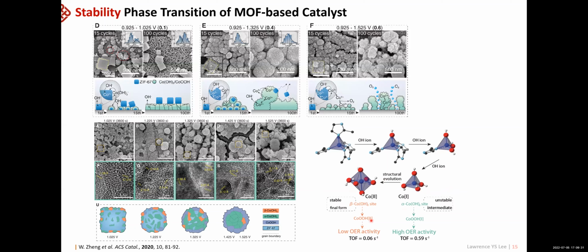So if anyone wants to use MOF directly for electrocatalytic reactions, you probably need to pay attention to their stability. I'm not saying the MOF is not a good electrocatalyst. They may be good pre-catalysts that can be used to generate active species. But in terms of rational design of electrocatalysts, it's quite difficult to predict what you will get from what you make.